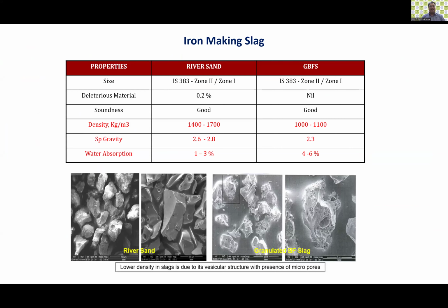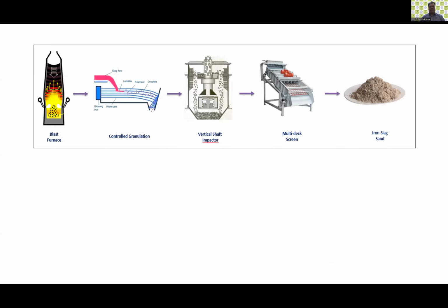What we have done here is we tried to investigate what could be done to this granulated blast furnace slag and convert it into fine aggregate. We made a comparison with river sand. We find that granulated blast furnace slag had lower density and lower specific gravity, and higher water absorption. Those were the primary reasons why it was tried but never commercially utilized as fine aggregate. At JSW Steel, we developed a technology by which we changed the granulation procedure during the iron making process by changing the water temperatures.